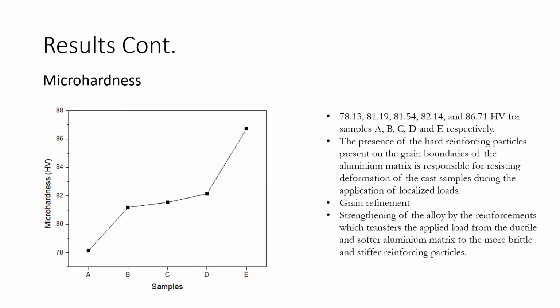Analysis of the microhardness showed that it increased with increasing weight fraction of the reinforcement. This increase can be attributed to the presence of the hard reinforcing particles, which were dispersed along the grain boundaries of the aluminum matrix. This dispersal ensured resistance to deformation of the samples during the application of the localized load. Another reason for the improvement in the microhardness with increasing weight fraction could be grain refinement. Lastly, the improvement in the microhardness was due to strengthening of the alloy. The strengthening of the alloy occurs by the transfer of applied load from the ductile aluminum phase to the brittle and stiffer reinforcing particle.